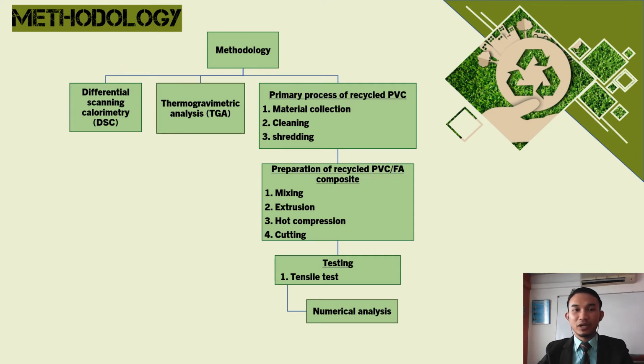Next, it continued with the compression process. In this process, I use hot compression with a temperature of 175 Celsius and pressure of 10 megapascal for 7 minutes. The compression process produced a PVC fly ash plate composite with 3 mm thickness. Lastly, I cut the plate into dumbbell-shaped specimens using a vertical saw, following the dimensions in ASTM D638 Type 1. After the preparation process, the composite will go through the testing process, which is the tensile test, and continue with numerical analysis.